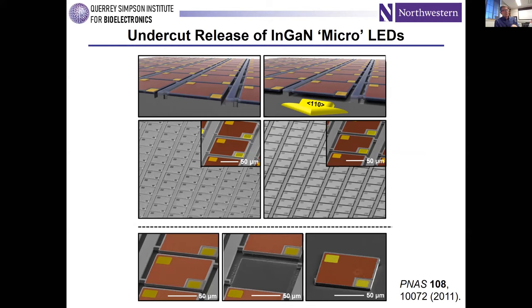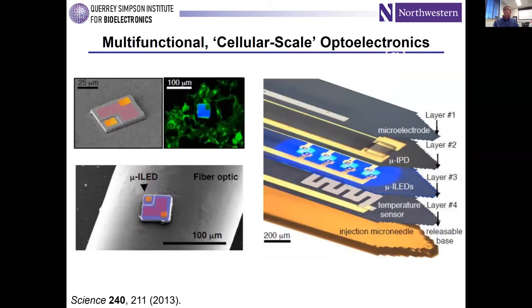The thickness is really defined by just the active material thickness that you need for operation of the device, thereby bypassing a lot of the constraints associated with wafer dicing approaches to create LEDs, the standard way to do that, where the thickness of the supporting wafer defines the thickness of the LEDs, and the precision of your wafer saw or your laser scribe defines the limits in the lateral dimension. So you bypass all of those constraints, and you can immediately start to build exceptionally tiny LEDs.